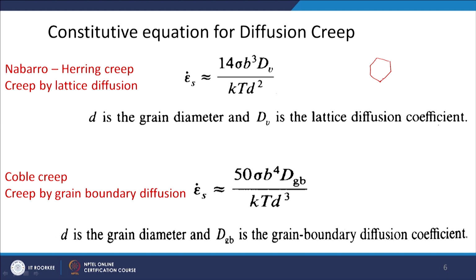Suppose this is my grain. These are the grain boundaries. When you have Nabarro-Herring creep, which is diffusion creep at low stresses, as I told you, dislocation will not be a mechanism here. So the creep will take place through a diffusion mechanism. Suppose I am applying stress in this direction, a tensile stress. When I apply tensile stress, you are creating more gap in this direction by stretching it. When you are creating more gap, you are creating a driving force for atoms to diffuse from this direction toward this direction.